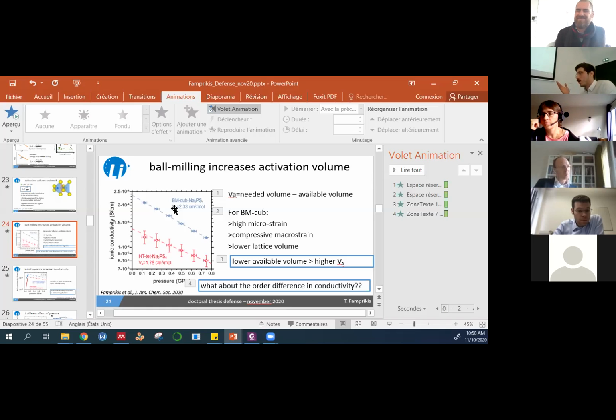But the other thing I would like to highlight based on your question is that the activation volume in principle only acts, or only increases the activation energy, in the presence of an applied pressure. So in order for it to actually have an effect at zero applied pressure, let's say, you would need to postulate some sort of residual strain on the material, which is not out of the question, but just a key small point there. Yeah, but it's basically what you're saying, right? That because of the mechanical synthesis, your phase is under strain.